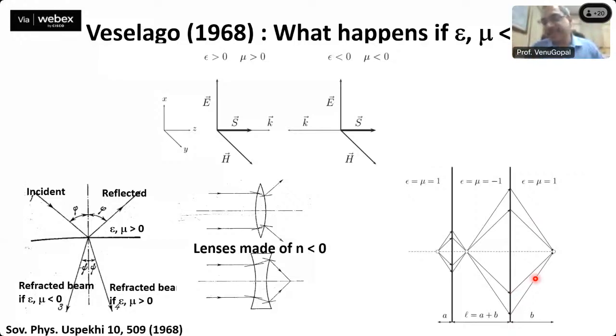So n is related because k is equal to 2 pi over lambda. Lambda inside a medium is lambda by n, the refractive index. So depending on the sign, your e power kx term will be changing in the plane wave. So he showed that basically we can get a perfect image because the high k vectors, which are basically evanescent, are no longer lost when you have a negative index medium confined between two positive index media, and it acts like a perfect lens with no loss of information in the image components from the source, object to the image.